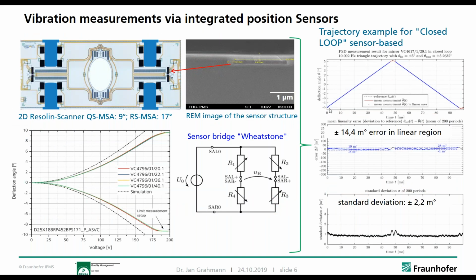Here on the right side, you see, in this case, a triangular trajectory was chosen. So we wanted to have a linear scan for the time of the blue line, and here again for the backward scanning. And of course, you do see nonlinearities here at the top. In this case, these are not used for the actual projection or imaging application.